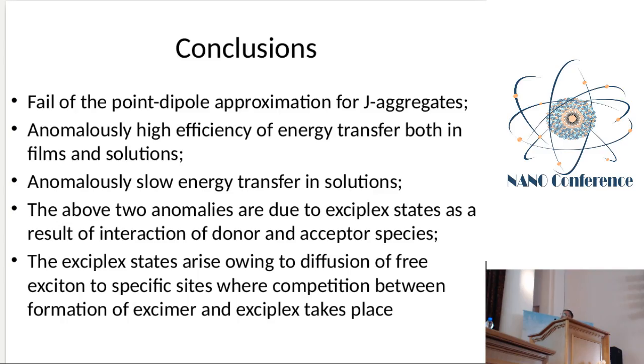In conclusion, I tried to show you that for large aggregates, J-aggregates, we have a fail of the point dipole approximation. We have anomalously high efficiency of energy transfer, and we have anomalously slow energy transfer in solution. These two anomalies can be explained by exciplex formation. And this exciplex arises due to the diffusion of free exciton to specific sites, where it competes with formation of excimers.